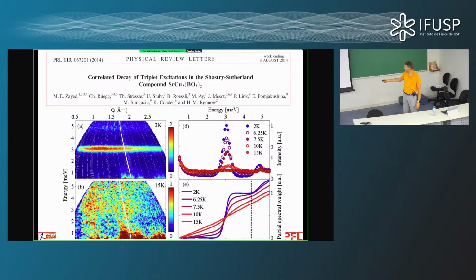And now if I increase the temperature, what would I expect? I have an excitation sitting at 3 millielectron volt. That corresponds to 36 Kelvin. So I would expect that if I increase the temperature to the order of 36 Kelvin, I would completely smear out my system. My beautiful product of singlets ground state would basically become a mess of fluctuating spins, and I would expect to see just a smeared out spectrum like this one here, if I increase the temperature to around the size of the gap in the system, so 36 Kelvin.